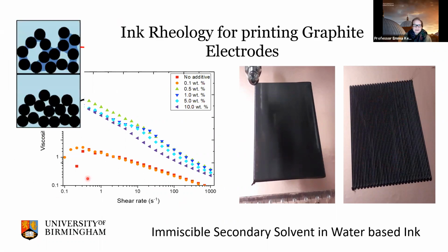And this happens by a capillary mechanism. So what happens is you put your secondary solvent in and it forms these little capillary joins between the particles, changing the thixotropy and also your viscosity of your ink quite considerably, even with tiny amounts of additive. And this was really important to make sure that we could actually extrude and print the ink through the little nozzles that you saw on that syringe.